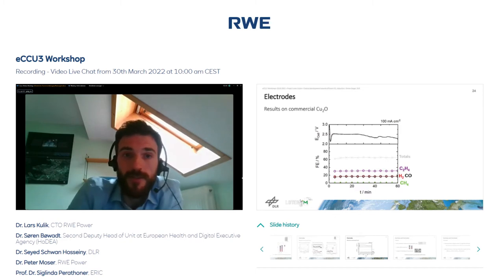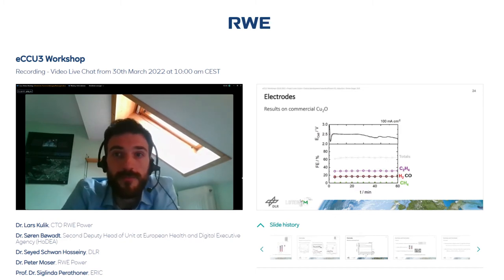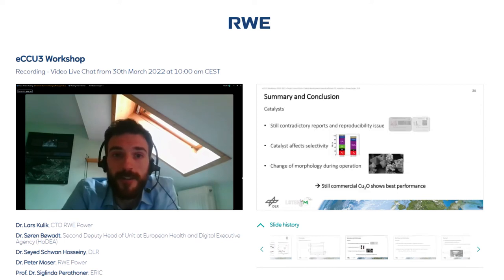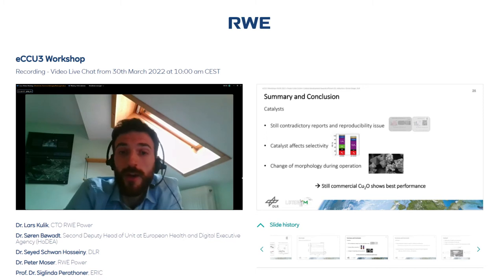And that brings me to the summary at slide 25. The summary of the catalysts would be that we have still contradictory reports and some issues with reproducibility. We know that the catalyst affects somehow the selectivity, but we also are aware that the morphology changes during operation, so there needs to be some more investigation.